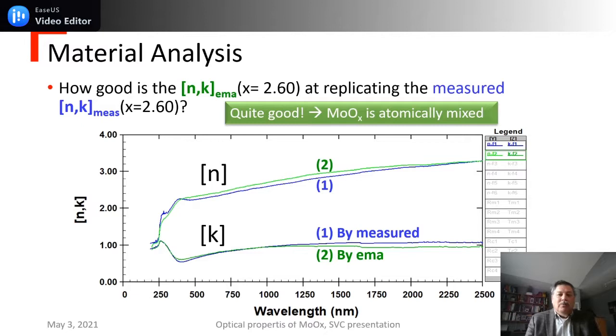And the answer is, for the most part, yes. The blue data, N and K, has been made by direct measurement, by direct solution of the R and T. And the green data is taking the endpoints at 2.0 and 2.9, varying the volume fractions, and you can see that the match is quite good. What this tells us is that molybdenum oxide, as we deposit it at ambient temperature, is a quite good mixture, an atomically mixed assembly of molybdenum and oxygen atoms.